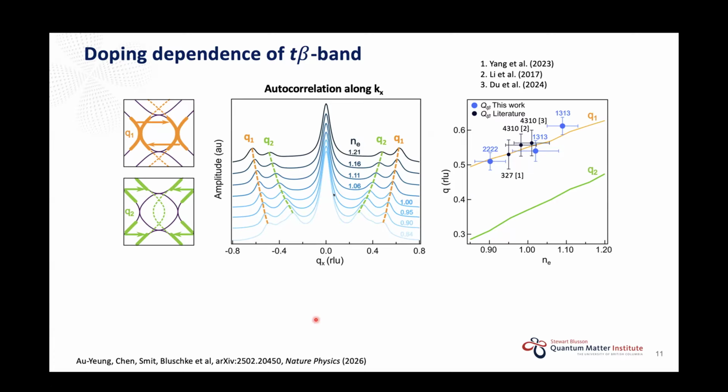Well, there's a lot we don't know, right? There are claims that you have a density wave in bulk to be able to see superconductivity under pressure. Yet in the films, as far as I know, no one's seen any evidence for density wave in any of the films. So there's a lot of mysteries. Yeah, I guess it's mostly a material problem. I cannot make it really pure. Plus, everything is probably very sensitive to the oxygen stoichiometry, which I think is still not as well understood as people claim it is.